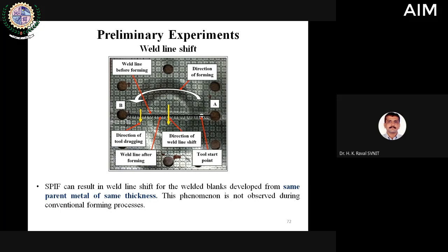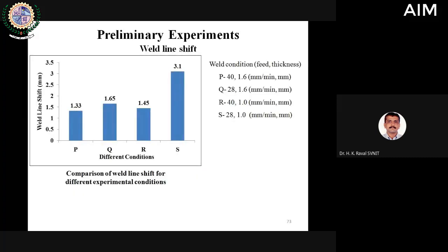So this is the pictorial image of the experimental results of weld line shift. Four different combinations were tried, P, Q, R, S. P stands for 40 feed and 1.6 thickness. Q stands for 28 feed and 1.6 thickness, and likewise R and S. The average weld line shift is recorded here, and it is observed that for the P combination the weld line shift is minimum, and R is second minimum, and that is for higher feed and for both the thicknesses.